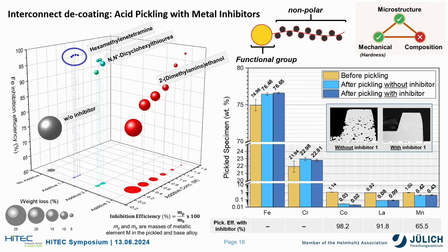Finally, pickling using this additive and under the best pickling conditions have yielded a cobalt pickling efficiency of 98% and a final cobalt content of 0.02 weight%. Now we are confident to say that we achieved the compositional limits of the target 304 steel.